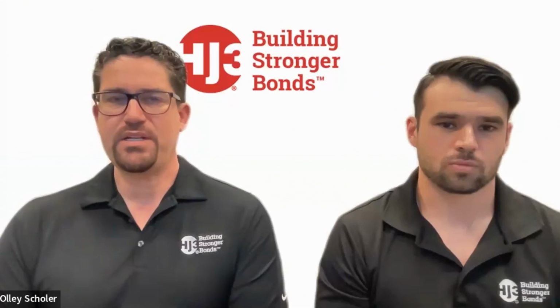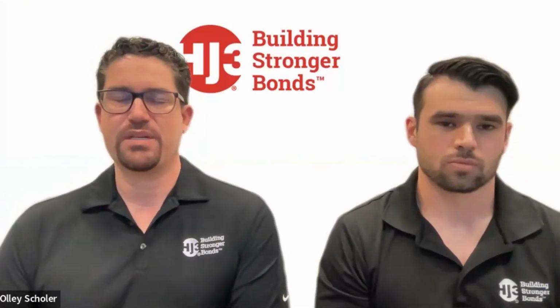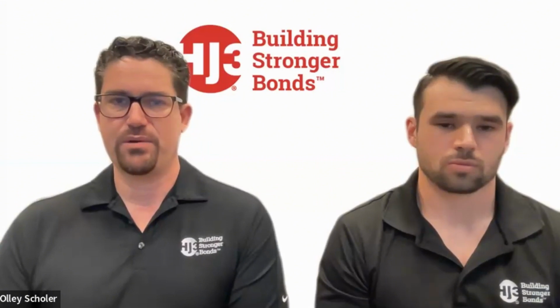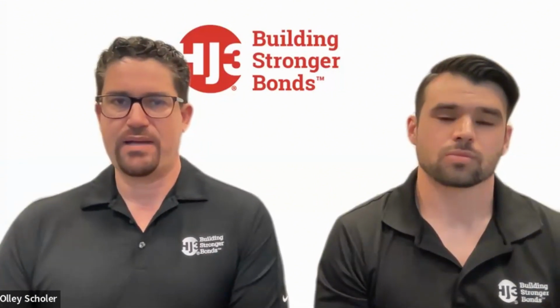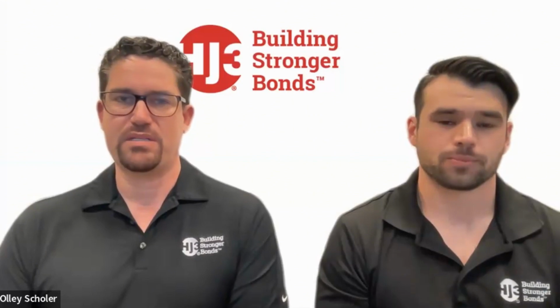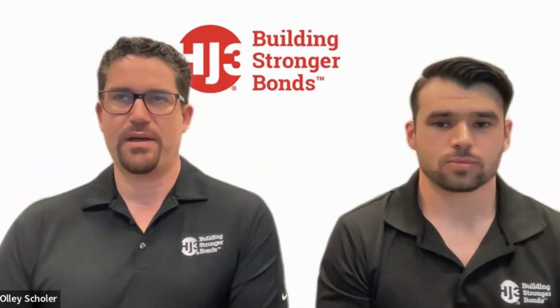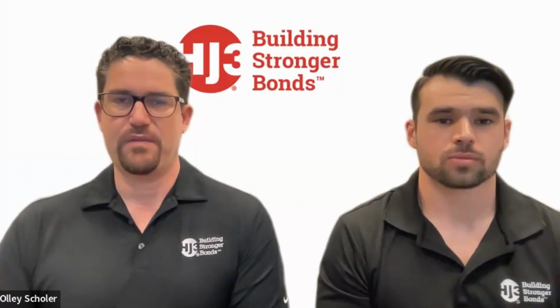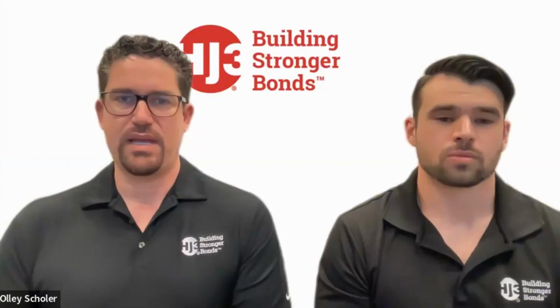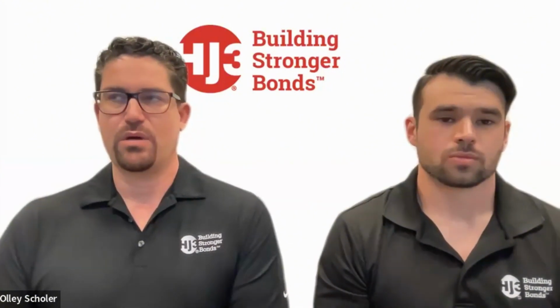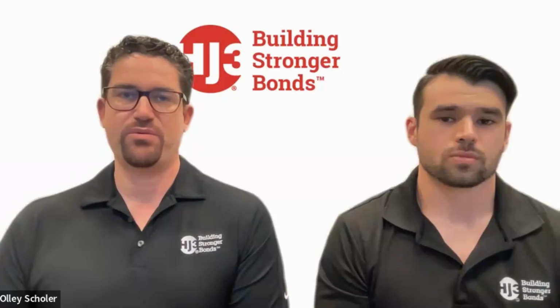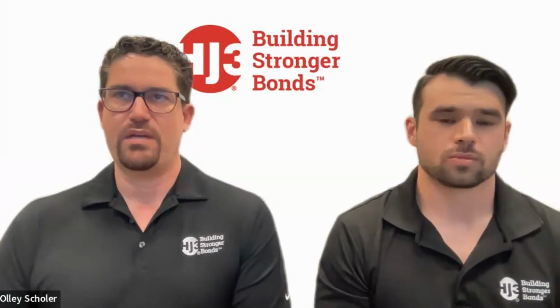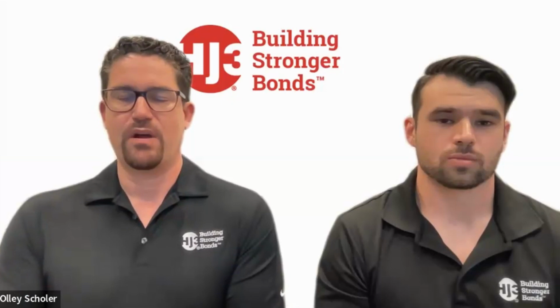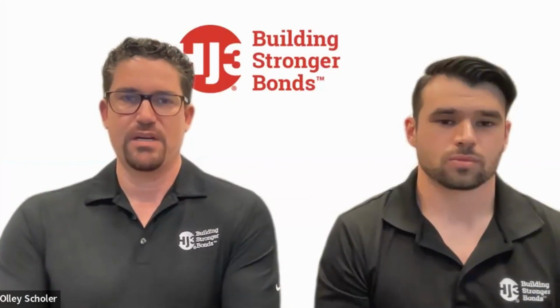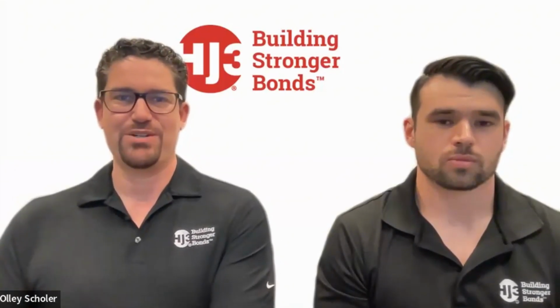In addition to the material side, we still do the burst tests. So AB 539, ISO 24817, and ASME PCC2 have outlined pressure tests where you can demonstrate the repair system's ability to handle pressure if, let's say, your wall loss is 80%. We also do the same level of testing for energy release rate, which is that value that you achieve when you test the carbon fiber over a through-wall defect. So it could be a 1/4 inch, 1/2 inch, or 1 inch hole.